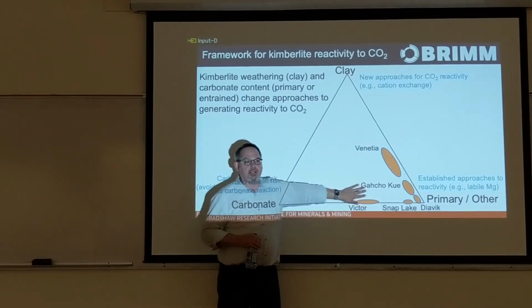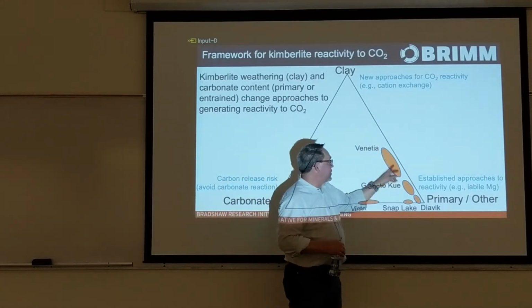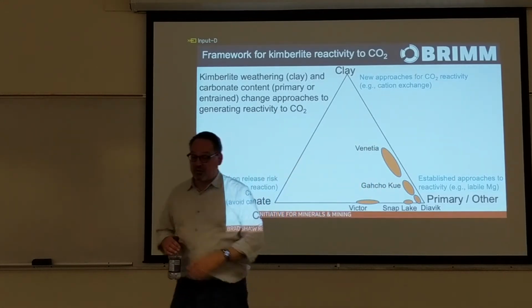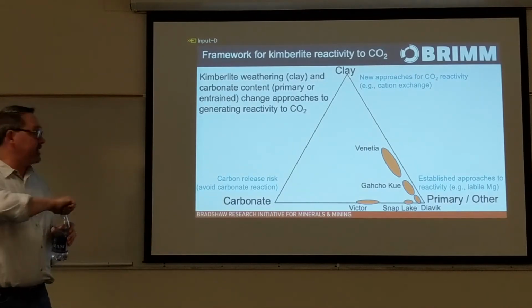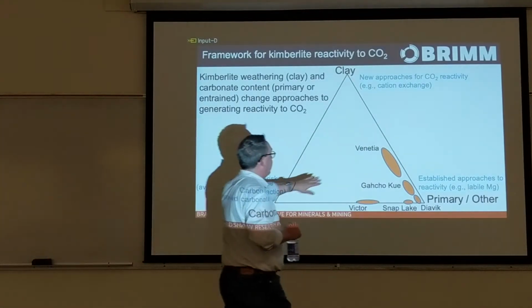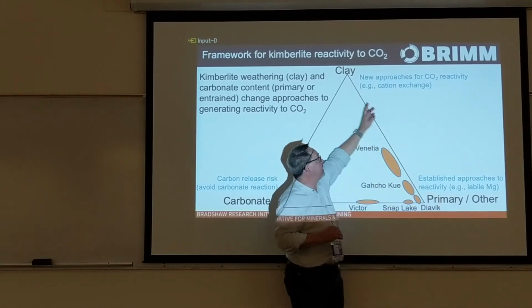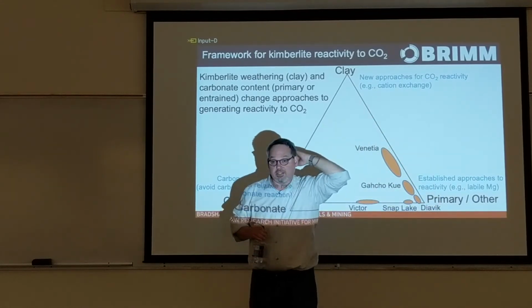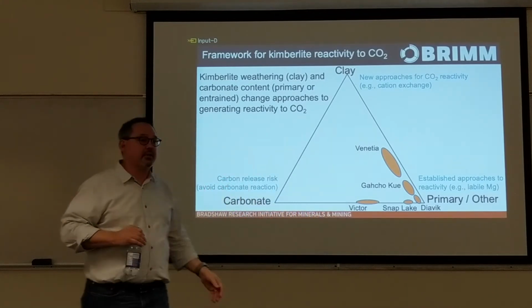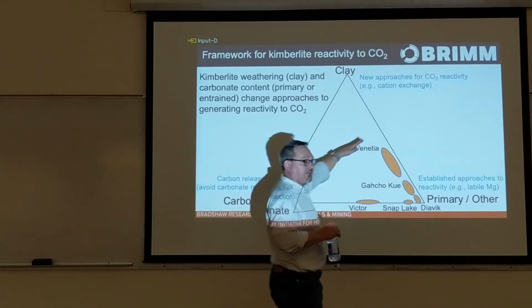So probably you would walk away from kimberlites that fall along in towards this axis here. The shallow facies at Venetia, and so we see probably something similar, all the crater facies that are up on this stuff, very, very clay-rich material, not really amenable to the approaches that we've taken to date, but we are looking at sort of cation exchange approaches that we might be able to use to get CO2 sequestration capacity out of clay-rich material, but it's nasty stuff.